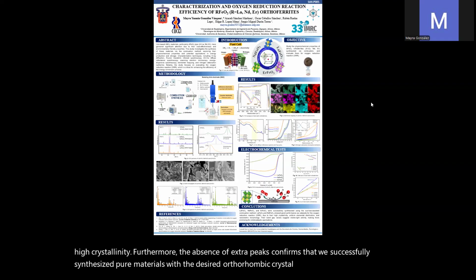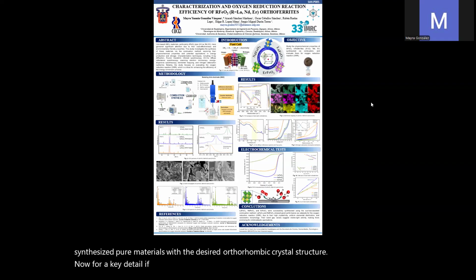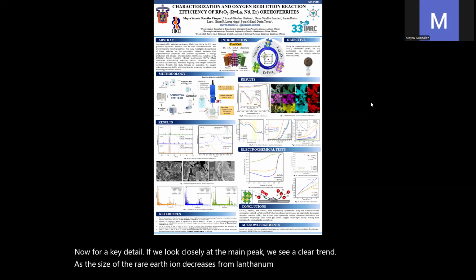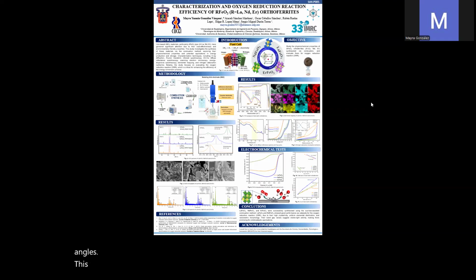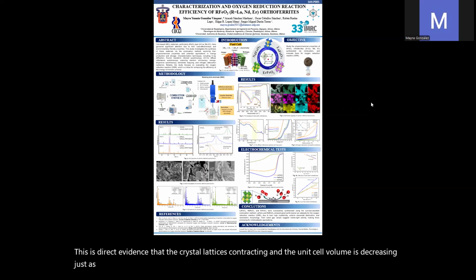Now, for a key detail. If we look closely at the main peak, we see a clear trend. As the size of the rare earth ion decreases, from lanthanum to erbium, the peak shifts to higher angles. This is direct evidence that the crystal lattice is contracting, and the unit cell volume is decreasing, just as we predicted.